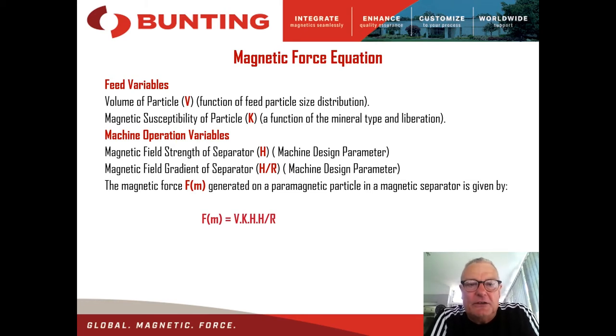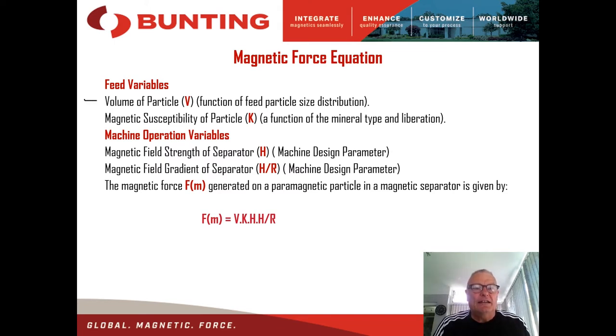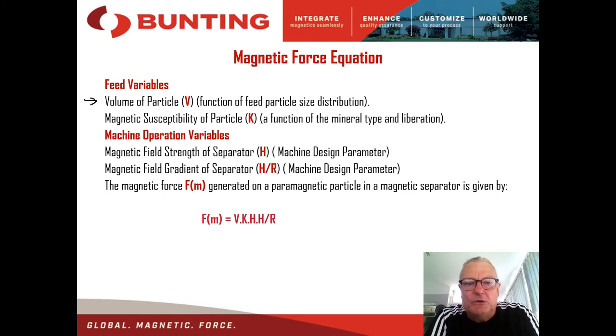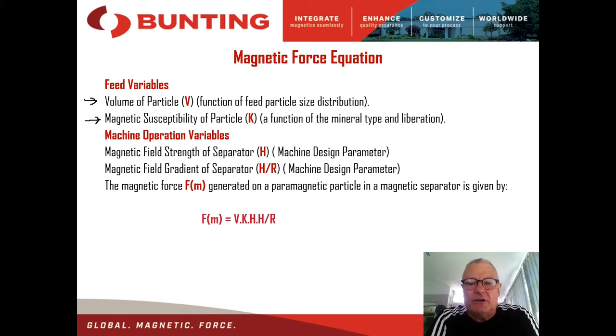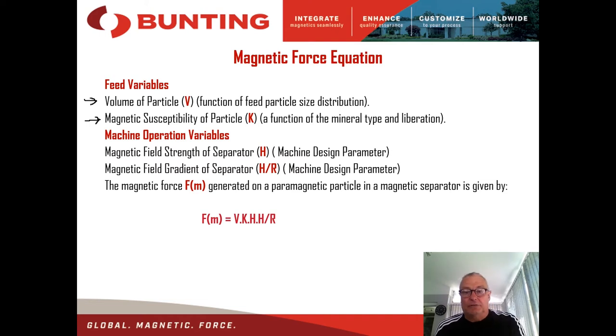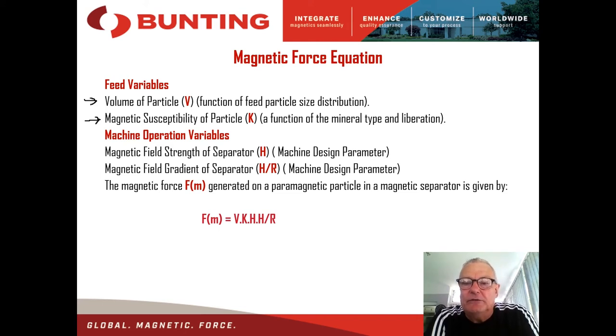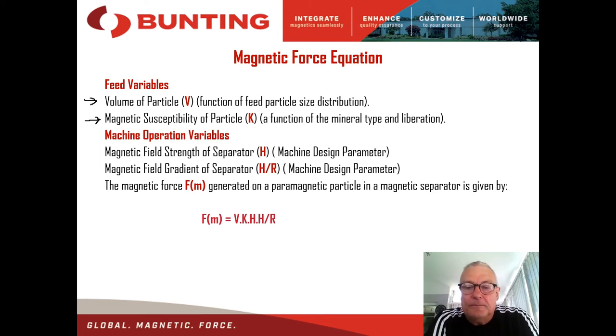As with all magnetic separation devices, there are certain factors we need to take into account in design and application. Feed variables include: the volume of particle, which is a function of particle size distribution, and the magnetic susceptibility of the particles being processed. Most materials we process will be minerals with a paramagnetic fingerprint, allowing us to separate them at different stages and get different concentrates. It's quite common from one machine to get seven different product streams, making this a very cost-effective way of processing complex beach sands, and niobium, columbite, and tantalum deposits.